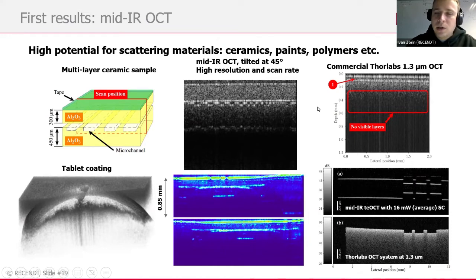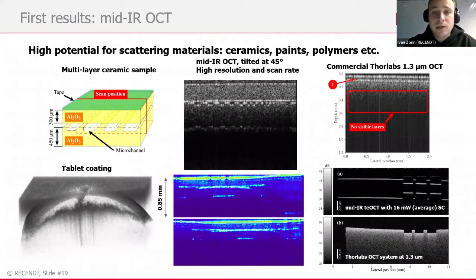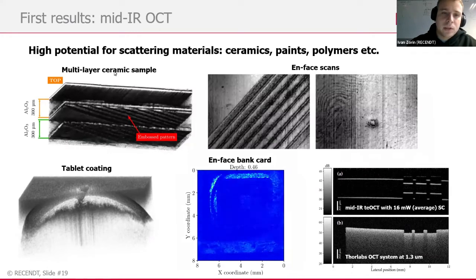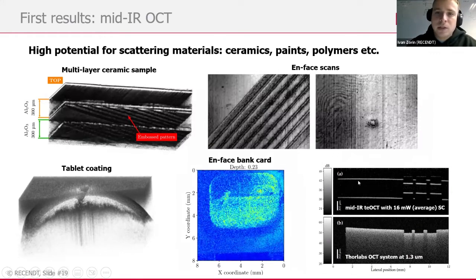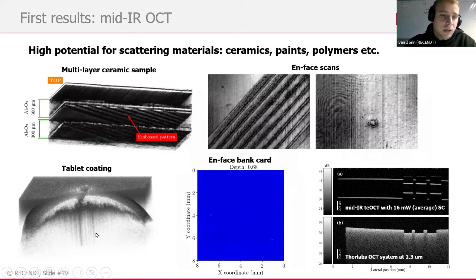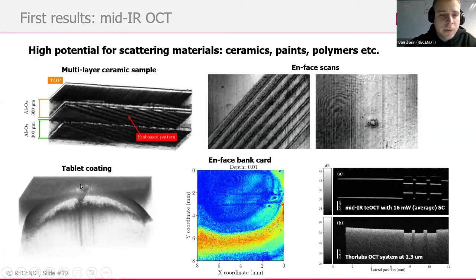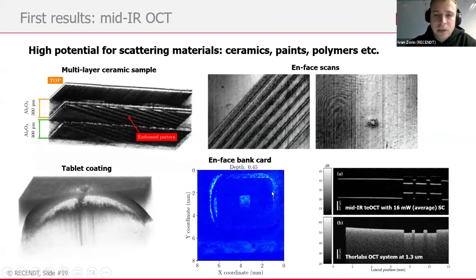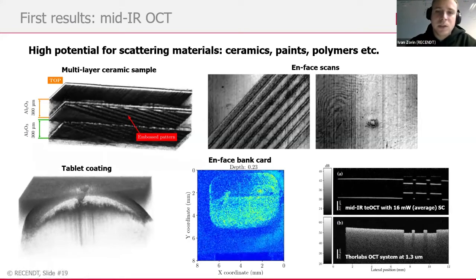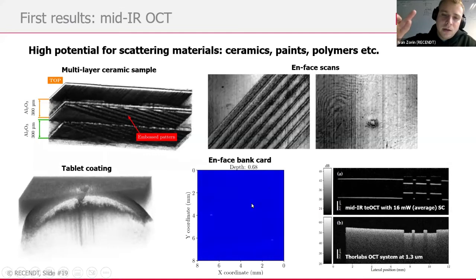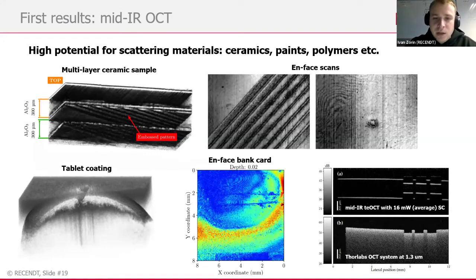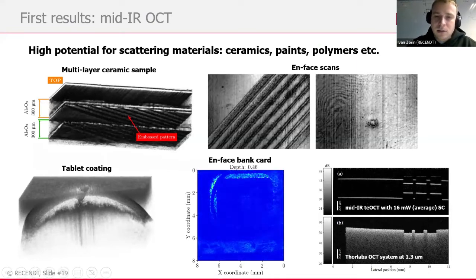This is a comparison of the ceramics sample with a commercial system at 1.3 µm, where no layers are visible. With mid-infrared OCT, volumetric scans of ceramic sandwiches with laser-sintered patterns can be measured and defects can be analyzed and evaluated. Also, a few measurements of tablet coatings and polymer samples — which are often very scattering — were performed. En-face images at different depths from a bank card show a chip inside, some antennas, and other details, demonstrating the capability to image through scattering polymer materials.